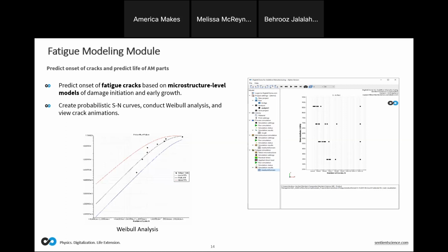As you can see on that SN curve, similar to experimental work, we are not providing only one data point, because we all know for fatigue, that's kind of meaningless. You cannot put one single life value for a load level, because fatigue by nature is stochastic and is sensitive to quite a few randomness in different parameters. When we are talking about surface roughnesses, the loading, the microstructure, all of them have randomness involved with them, and because of that, fatigue by nature is stochastic and random. That means that if you make 10 dog bones, put them under the same loading, you're going to get a range of fatigue life instead of a single value.